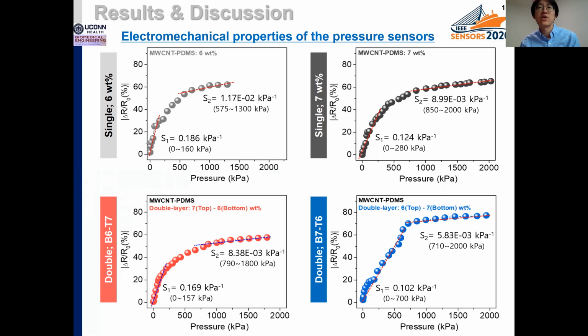In the case of the stacked double layer sensor, which is B6 T7, this sensor shows a similar trend to the single layer sensor with 7%. This result indicates that there is no improved performance. On the other hand, the B7 T6 sensor exhibits an excellent linear range up to around 700 kilopascals and a wide pressure range of 2 megapascals, which shows great potential in the field of wearable devices.